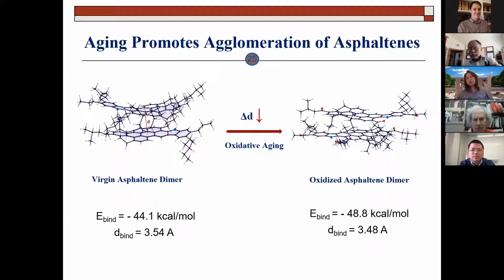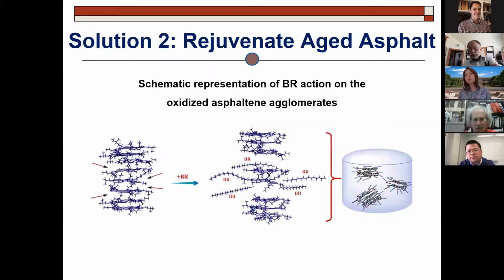So if you get more of these layers attached to each other, what happens? You're going to get these large agglomerates that happen on the left. And you don't want that, because all those bad things I just told you about are because of those agglomerates. So we have to break the agglomerates. If a rejuvenator truly rejuvenates, it should be able to diffuse into this agglomerate and break it apart, reducing the agglomeration size. Here, for instance, from this big one in the schematic, you can get these tinier ones, and you are reversing a bit of the bad effects, but not chemically. I'm not taking away the oxygen that is already bonded to them.